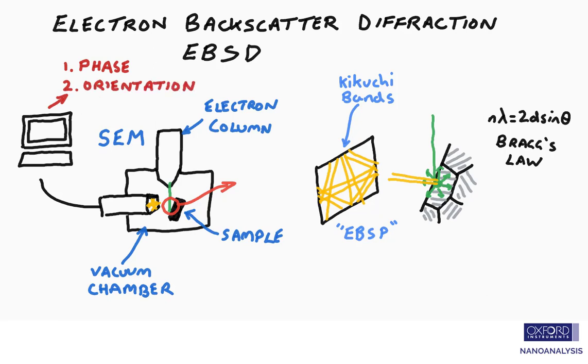It can do this with very good specifications. The spatial resolution is on the order of tens to a few hundreds of nanometers, the precision with which we can measure the orientation is typically a fraction of a degree, and the speed with the latest CMOS-based EBSD detectors can be up to 5,000 indexed diffraction patterns per second.